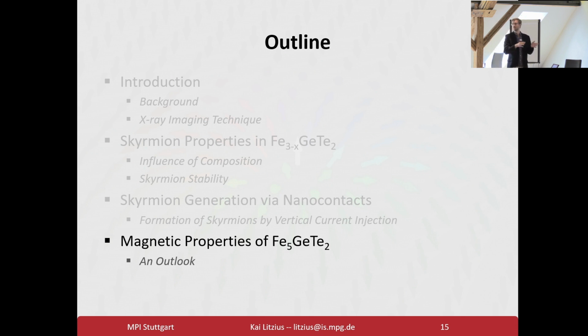This is a different van der Waals system. Essentially, it's similar because it's still the same components, but it has a higher iron content. And this is particularly interesting because this van der Waals system has a very high Curie temperature. Usually van der Waals systems have comparably low temperatures, and for any kind of device, of course, you want it to be as high as possible.